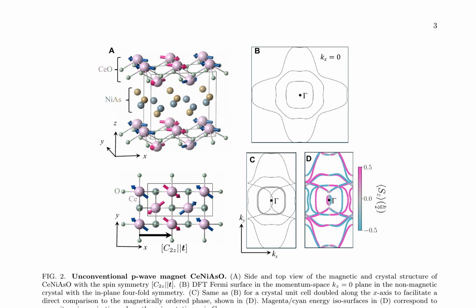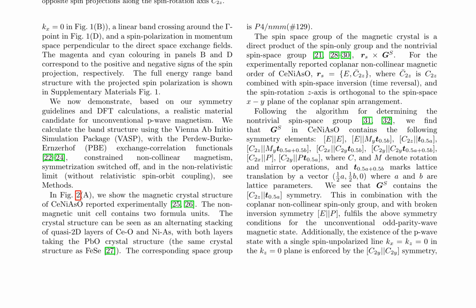The spin space group of the magnetic crystal is identified as a direct product of the spin-only group and the non-trivial spin space group Rs times Gs, where Rs equals E, C2z, and Gs contains symmetry elements E, M0.5b, C2z, T0.5a, and others. The existence of the p-wave state with a single spin unpolarized line kx equals kz equals 0 in the kz equals 0 plane is enforced by the C2y, C2y T0.5a plus 0.5b symmetry.